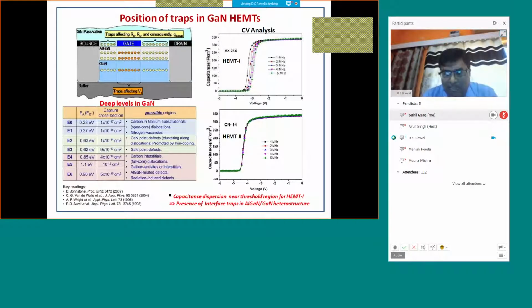And one quick way of studying the presence of these traps is the CV analysis. When we do capacitance voltage analysis at variable frequencies, you can see the CV curve behavior depending on these traps, because they respond to a particular frequency because of their fixed time constant. So you can see that this CV graph is with respect to two different HEMT structures. Here, where capacitance is falling suddenly, it means I am at the interface of GaN and aluminum gallium nitride, and this is indicating the presence of traps near the interface, whereas in this there is no variation with the frequency in capacitance. So it means that there is least possibility of finding these traps at the interface. So the interface is good for this HEMT2 structure, whereas it is bad for HEMT1 structure.